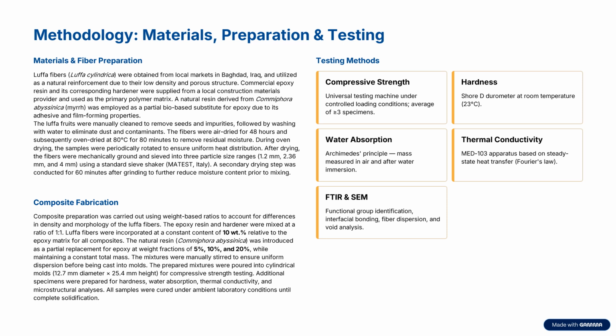The epoxy resin and hardener were mixed at a ratio of 1:1. Luffa fibers were incorporated at a constant content of 10% relative to the epoxy matrix for all composites. The natural resin was used as a partial replacement for epoxy at weight fractions of 5, 10, and 20%, while maintaining constant total mass. After that, the prepared mixture was poured into cylindrical molds for the compressive strength testing.